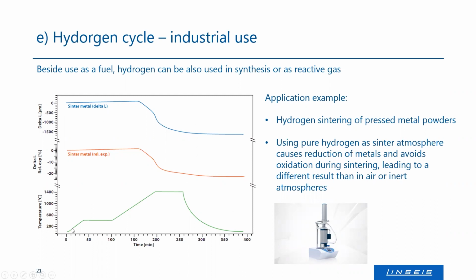A typical sinter curve and typical sinter process looks like this. The green curve down here shows your heating. So you heat your sample to a first target temperature where all your volatiles and all your humidity is evaporating. Then you have a little holding time, and after that you have a heating to your sinter temperature. During that heating step to high temperature, the materials, your metals, your raw ceramics start to burn. They start to react with each other. They start to get rid of carbon dioxide, carbon monoxide, and so on. And they form your final product.